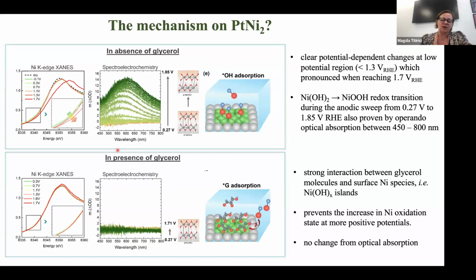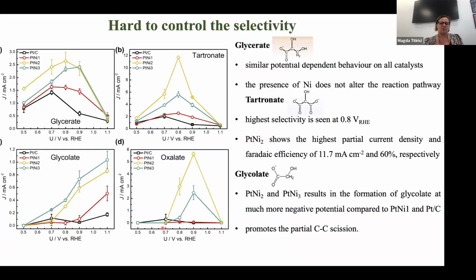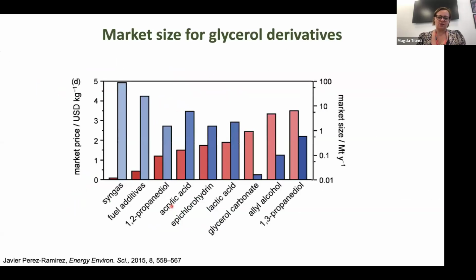When you have glycerol in your system, it seems that glycerol really absorbs and stacks on your catalyst, and it prevents this nickel from further oxidizing to nickel oxyhydroxide. So you will maintain these nickel oxide islands on your catalyst, and this nicely correlates with spectroelectrochemistry where you see no change as well. Anyway, this was a nice study, but we couldn't really control the selectivity on any of these catalysts towards a particular product, and we got a mixture of acids.